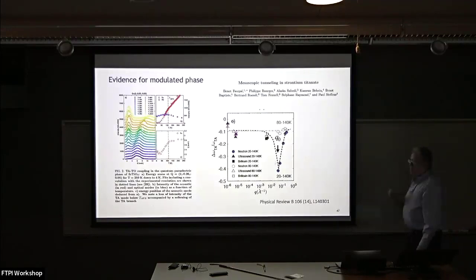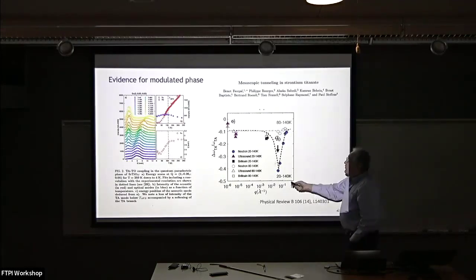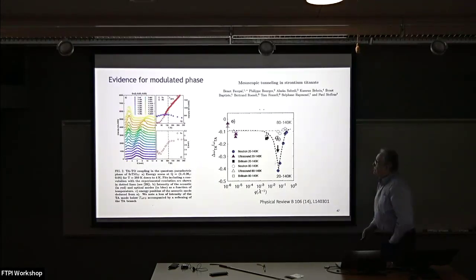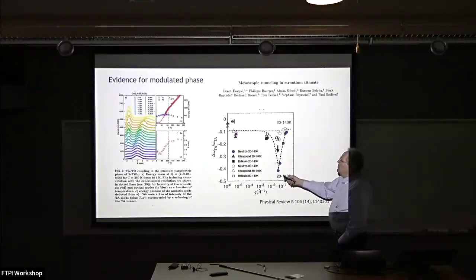Okay. Is there any evidence? And we're doing all of this, and then we got scooped by this paper. This is neutron scattering data, and let me talk you through this figure here. What you're looking at is from high temperature, the yellow curves, to low temperature, which is the darker blue. The measurement is being done just off of the Bragg peak, 0.05, 0.05.